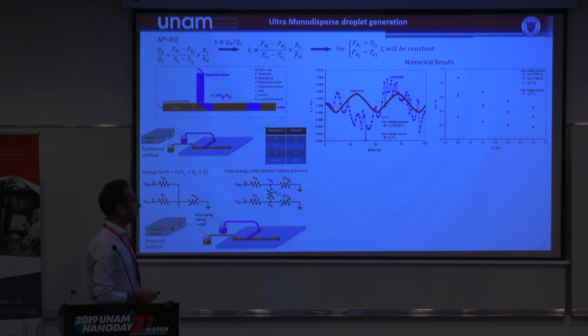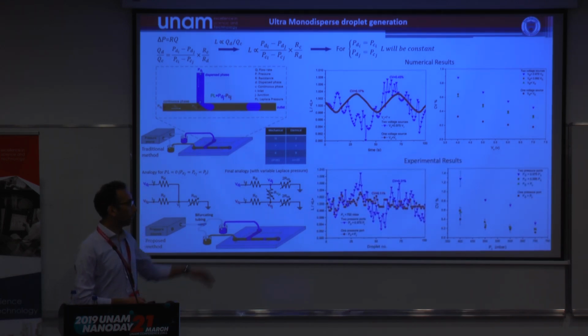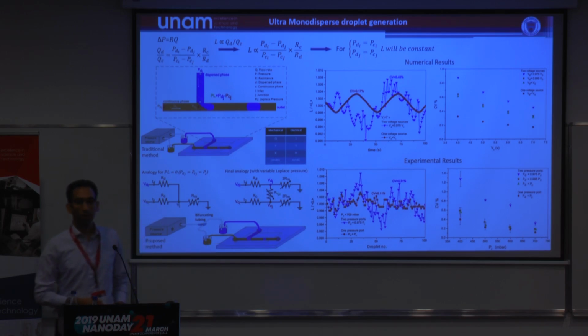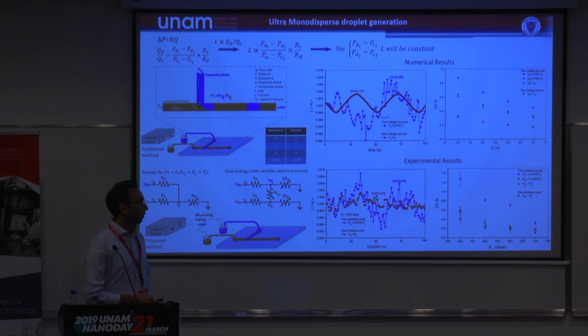We did the same for the experiment. We used this bifurcating tubing in order to have a single port of the pressure pump and supplied identical pressure. And we had these results, which had a good agreement with the numerical results. We could get a CV equal to 0.11%, which is a world record to the best of our knowledge. So far, the best CV which has been reported is 0.40%, but ours was 0.11%.